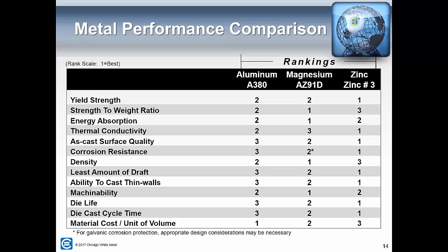Magnesium is in the middle, though I do have an asterisk by it because magnesium in plain atmospheric corrosion tests slightly outperforms aluminum. It's pretty close, but it does suffer from a potential galvanic corrosion. So that has to be considered, and again, that's why we would need to ask questions about what it's mounted to, what is the atmosphere that it's in, and so on. Density, magnesium is the least of weight and zinc the heaviest. Draft analysis, you can see how that breaks down, zinc being preferred.